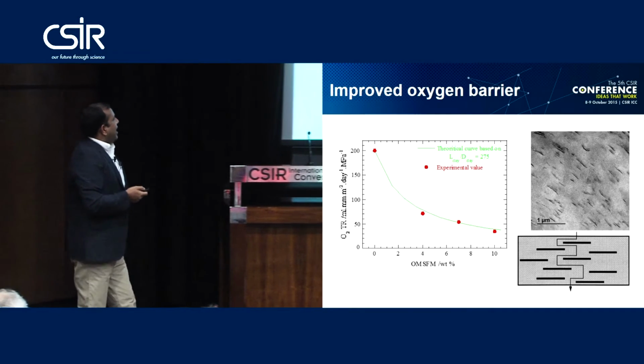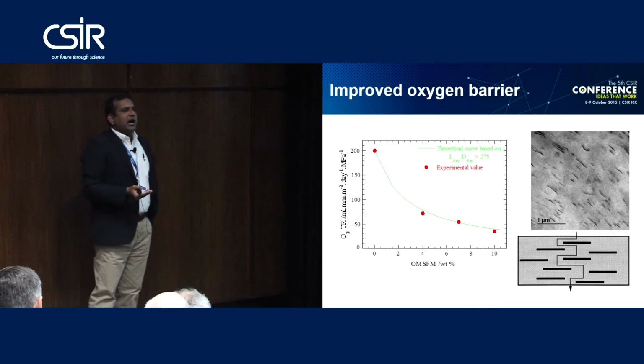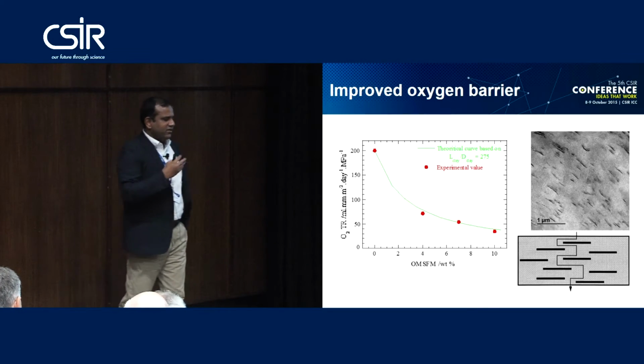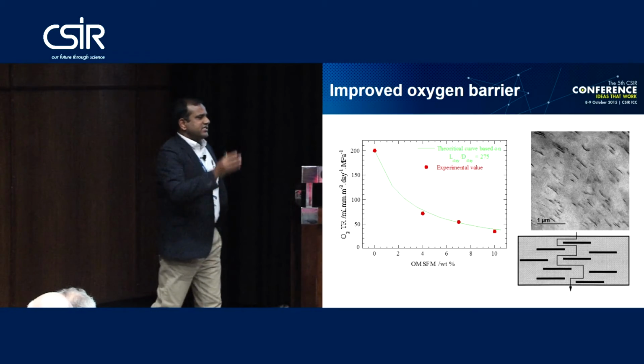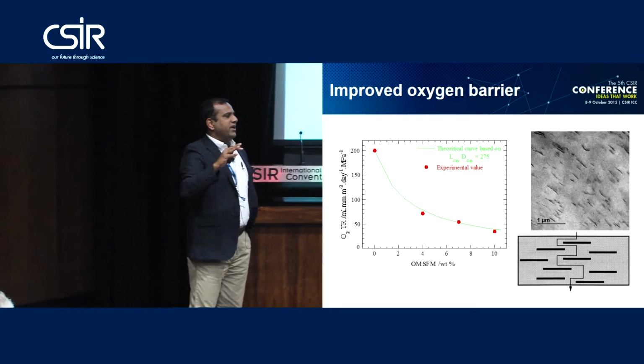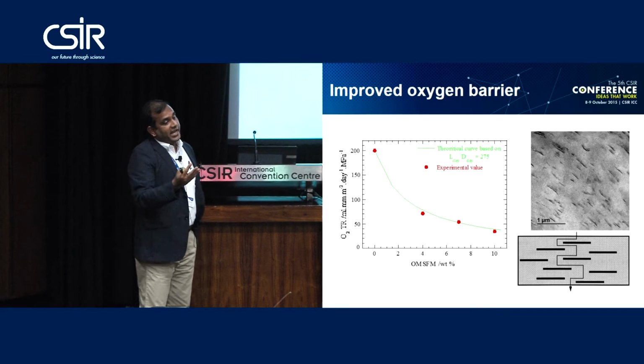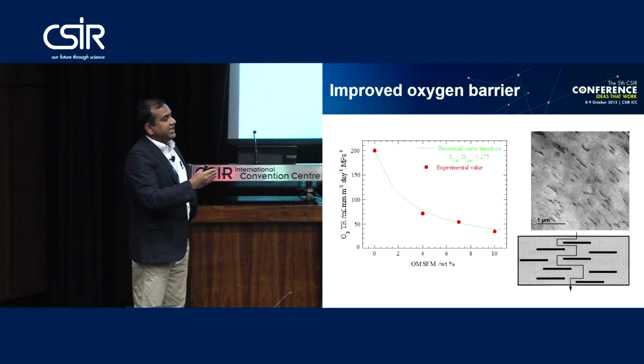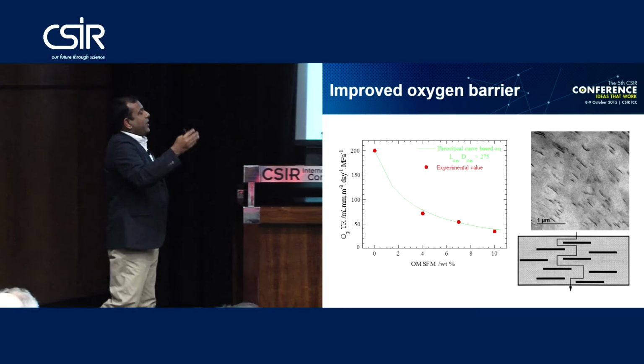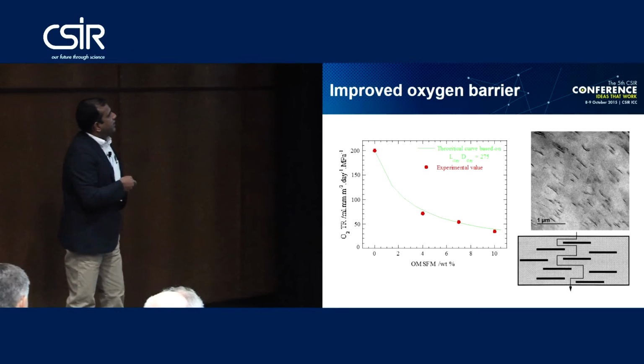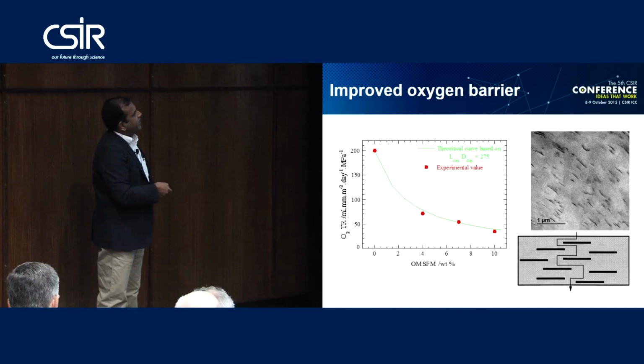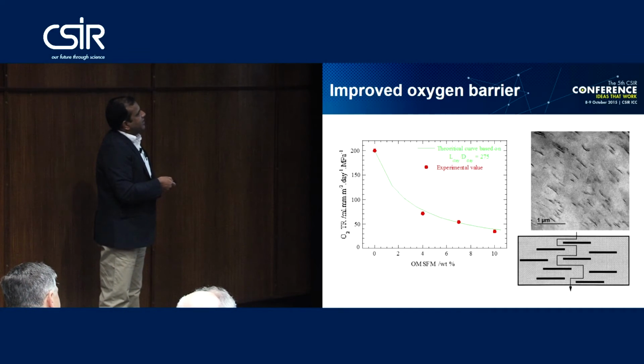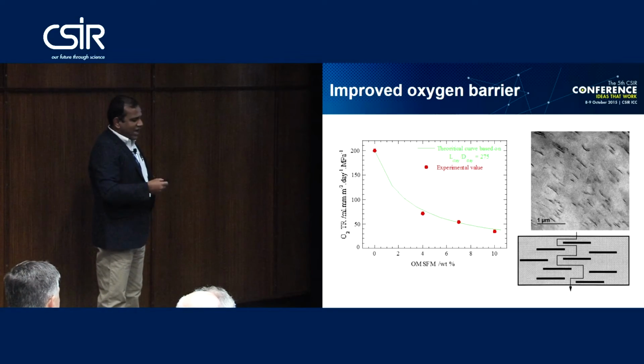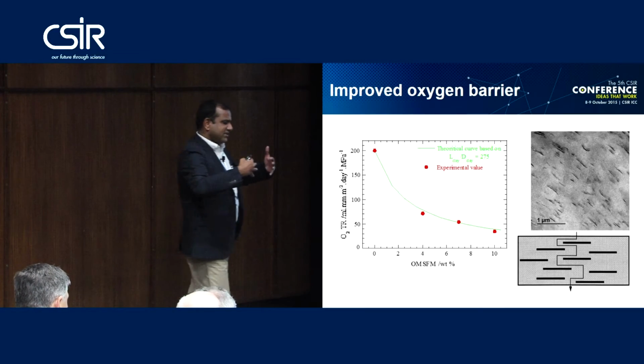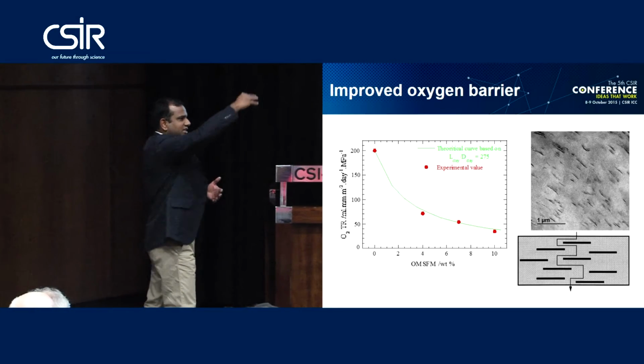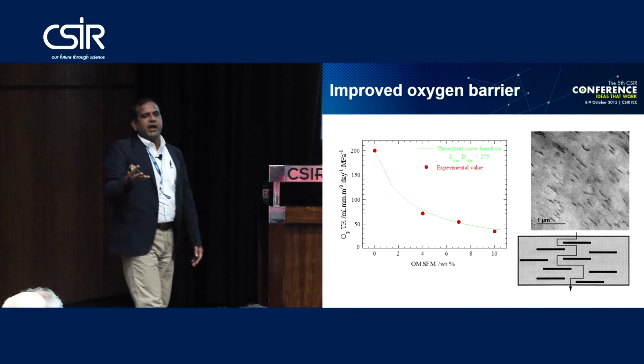So for our technology, what we are trying to do now is develop materials that have the same level of barrier properties. It would be great if we get 1 layer, that means only composite, but our target now is up to 3 layers. To improve the barrier properties, the simple rule is you need the dispersion and orientation of nanoclay platelets in such a way that they delay the passage of the gas molecules inside your matrix.